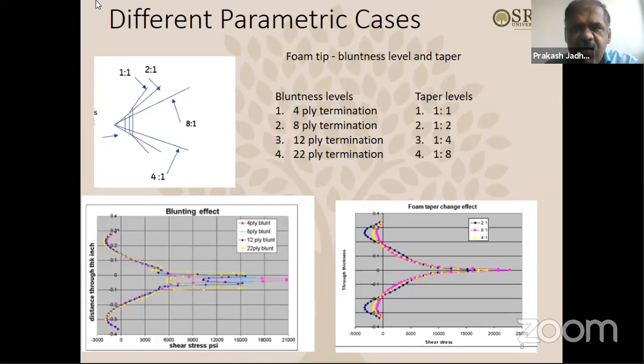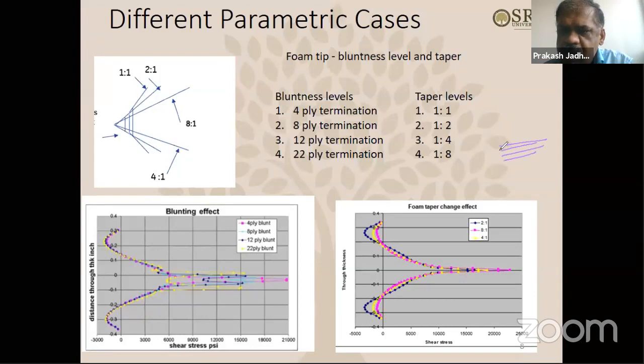I'll show you a demonstration. Blunting means what? If these plies are coming like this, 1, 2, 3, and 4, so 4 plies are ending at the end, and there is this tip here. That means you have a blunting of 4 plies, 4 plies terminating at the end. Like this 4 ply termination, or you can have 8 ply termination, or 12 ply termination, or 22 ply termination. Basically, all these plies come to the end and end there. So 4 plies ending is called the 4 ply termination. Another case is 8 ply termination. The third case is 12 ply termination.